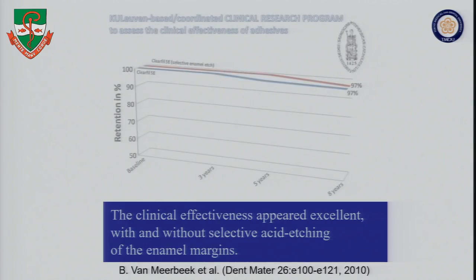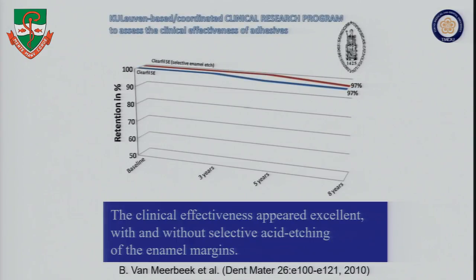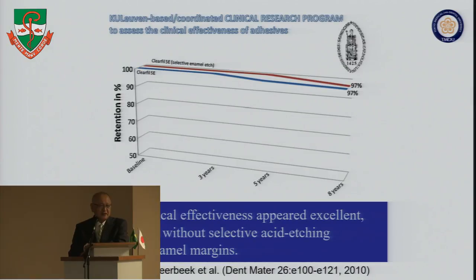We had a very excellent clinical evaluation by Dr. Bart Van Meerbeek from Belgium. They evaluated the longevity of the restoration at the cervical region with and without the selective enamel etching in the case of Clearfil SE Bond. So after 8 years of the restoration, both of the groups showed almost the same percentage of the retention.